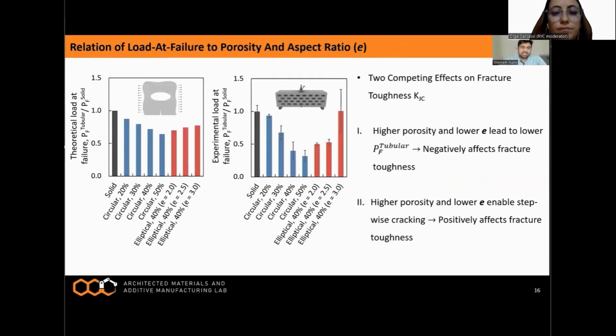Using the relationship between the SIF ratio and the load at failure, we have also plotted the theoretical load at failure for different porosity and aspect ratio. We can see that the theoretical load at failure decreases with an increase in porosity and increases with an increasing aspect ratio. The theoretical trends for the single tube also match the experimental trends of the load at failure for a fully tubular system. The results regarding the load at failure indicate that the tubular system with higher porosity and lower aspect ratio exhibits a lower load at failure, which negatively affects the fracture toughness of the cement-based material.